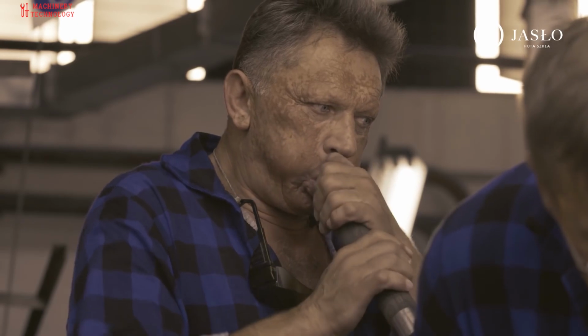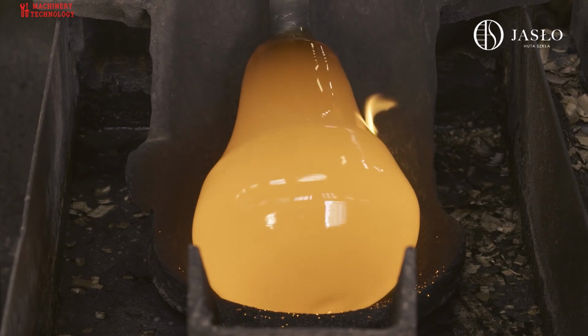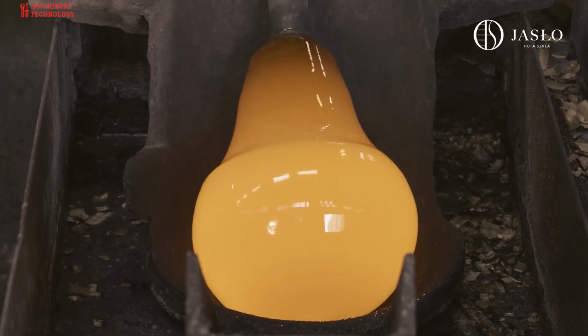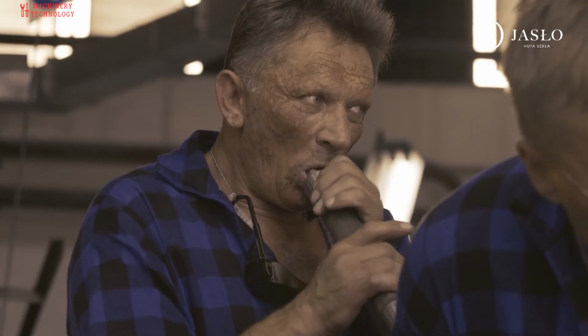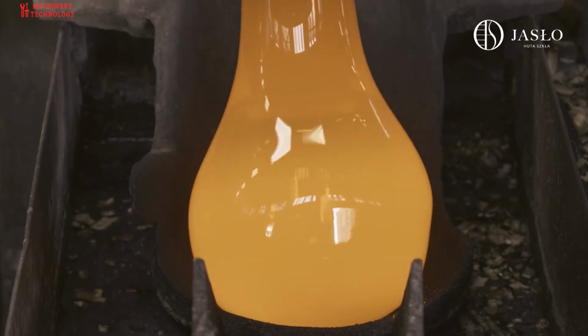A hollow blowing iron pipe is dipped into the molten glass, which is rotated and gathers the glass. This is then rolled on an iron slab to form the parison. It is further manipulated by reheating and blowing so that it is formed into the rough shape of the mold. This is then transferred to the final mold, which is wet with water.